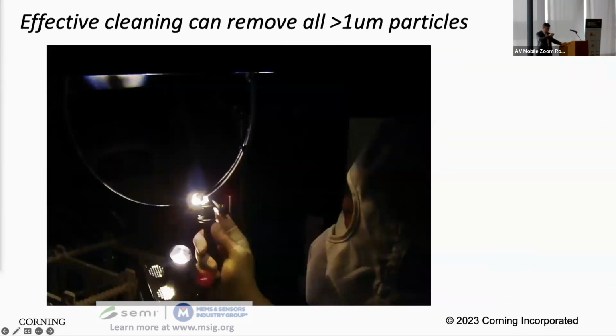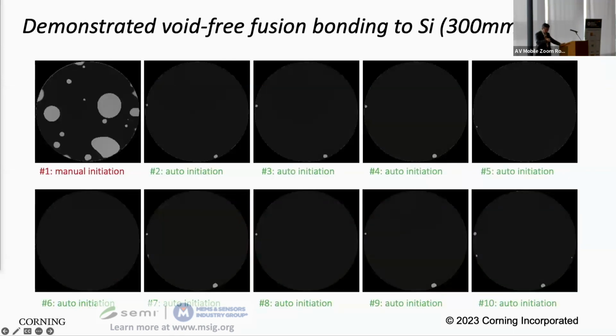And by keeping the glass extremely clean and the silicon extremely clean, we can do fusion bonding between the 2 materials with very good quality. In this case, we have 10 wafers, and we used a commercial bonder. If you don't do the initiation of bonding right, the number 1 wafer shows you trap a lot of air. But if you use the machine's initiation mechanism, 9 out of 9 came out bubble-free in the center of the bonded wafer. And the only defectivity you see is always at 5 o'clock or 9 o'clock. This is due to some handling defects when we made the glass wafers.